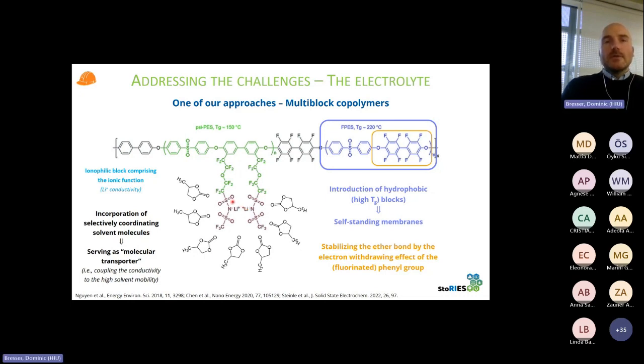But somehow, of course, also improving mobility, right? Because a coordinated lithium cation can apparently move easier than a naked, so to say. And then, of course, in addition, these coordinating small molecules in the ionic domains improve the mobility of the side chain, right? And then basically by just some sort of statistics, reduce the time that is needed that two side chains are sufficiently close to each other so that the jump gets possible. So they play several roles, so to say, but as said, the high dielectric constant is important so that they can nicely coordinate the lithium. And then we can decouple to some extent conductivity, right, and the polymer dynamics.